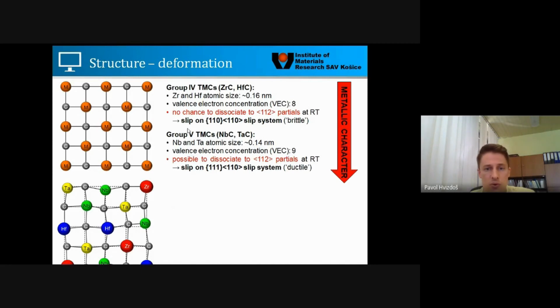In case of group 5 transition metals, which comprise niobium carbide, tantalum carbide, and also vanadium carbide, which is not indicated here because we did not deal with that, they have an extra electron on their outer shells, and therefore they have more metallic character, which I try to indicate on the right side. And this metallic character makes possible the dissociation of dislocations into partials on the 111 plane. And therefore the 111 plane can be activated even though the critical resolved shear stress for this specific slip system is higher than that one.